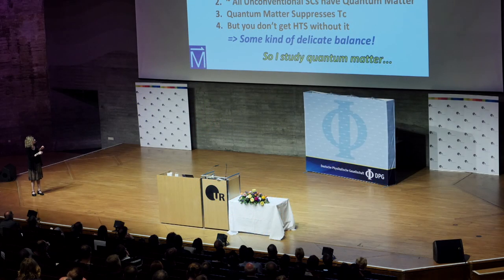And as I mentioned, one side is the insulator, one side is the Fermi liquid, and the superconductivity is in the center. Approximately all unconventional superconductors have this strange behavior above the superconducting dome. One thing you're figuring out here, and there have been a lot of measurements to support this: on the highly correlated side, where you have the bad metals, we see a dome, so Tc goes down. Too much correlation kills the Tc. Over on the Fermi liquid side, Tc is also going down as we increase the hole doping or the pressure or the field or other thermodynamic parameters.